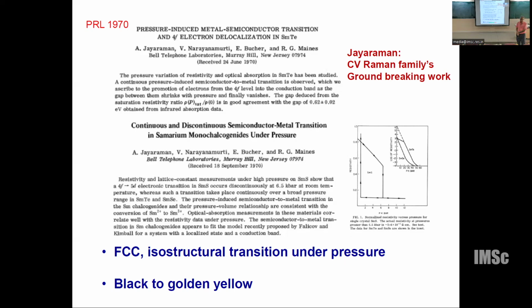For his own reasons he went, but he published very beautiful results on different materials in quantum physics. What he did is he took samarium sulfide, selenide, telluride. They're all semiconductors, black material. When he applied pressure of 6 kilobar, it becomes golden yellow. You start with a black material and apply pressure. In fact, you don't even require a pressure cell. You take the material, put it in your porcelain mortar, just grind it, and it becomes golden yellow. That's all the pressure required, very small. You can see it with your own eyes. And when you release the pressure, it comes back to black.